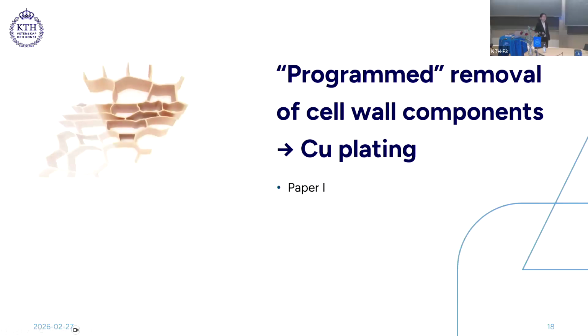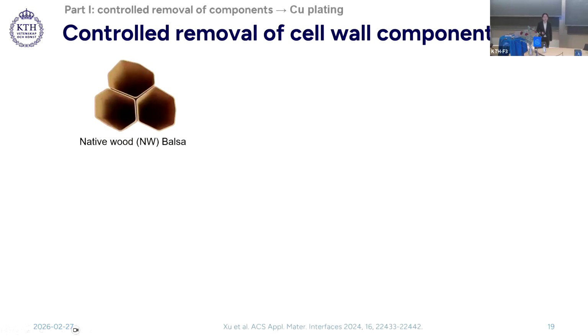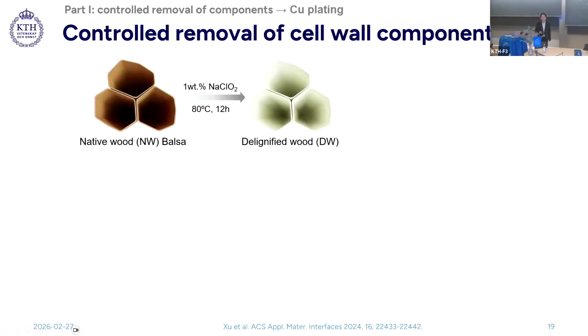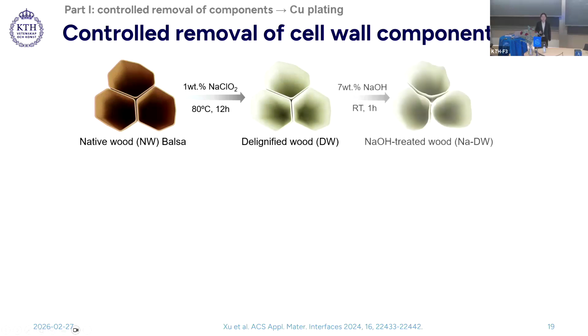Let's start from the first one, programmed removal of cell components, followed by copper plating. In this work, we used balsa wood as a starting material due to its high porosity. Chlorite delignification was then performed to selectively degrade lignin. The delignified wood was then subjected to a mild alkaline treatment using sodium hydroxide at room temperature for 1 hour.